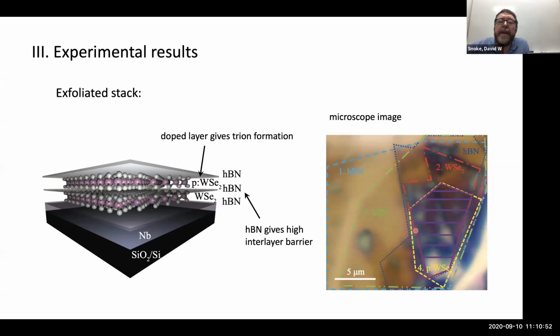I have to say that apart from the nice oscillator strength and binding energy that you have for these monolayers, the fact that we have HBN to make a really good insulator is also a really important part of this, because you don't want a lot of tunneling and a lot of current in the vertical direction. You want these things to be well separated. And that was always a problem with the gallium arsenide: if you tried to make this complex in gallium arsenide, the barrier height is not so high, you always end up with tunneling through that barrier.